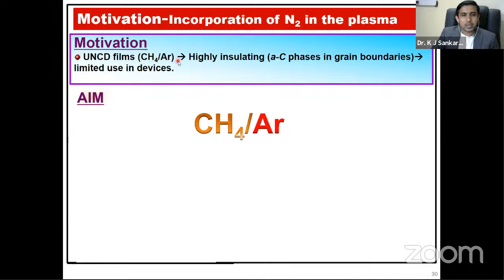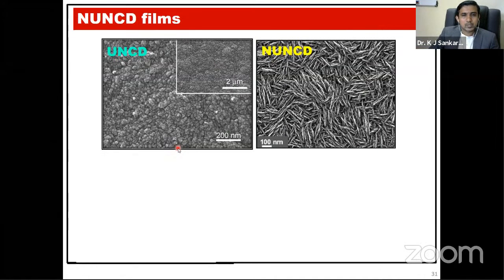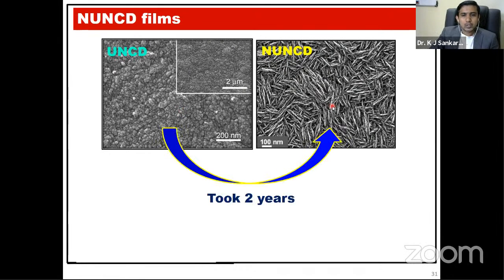As I mentioned again, methane and argon plasma grown UNCD films are highly insulating. Even in the presence of amorphous carbon, they are not highly conducting. So we cannot use those UNCD films in some field electron emission devices. So for the UNCD films grown in methane and argon plasma, I am going to replace the methane argon with methane and nitrogen. So what happens in this methane and nitrogen plasma? Here you can see that the UNCD films with spherical grains converted to a nitrogen UNCD with wire-like structures. So a big change in the morphology occurs, but this change took me 2 years.